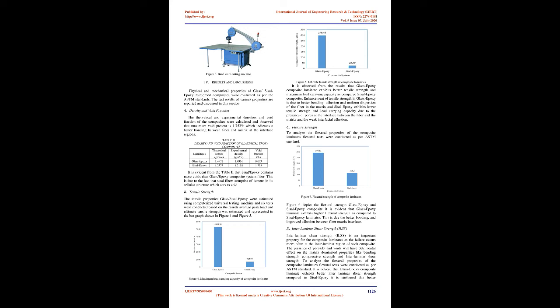The chemical treatment modifies the fiber surface properties, which enhances interfacial adhesion between the fiber and the matrix, and improves mechanical properties. Hence, in this research work alkali-treated plain woven sisal fabric was chosen to fabricate glass/sisal hybrid composites. Further, in this work to achieve uniform distribution, to minimize the void formation and to get uniform thickness of laminates, fibers in plain woven fabric form supplied by Sri Lakshmi Group Exports and Imports, Guntur, Andhra Pradesh, India was used.